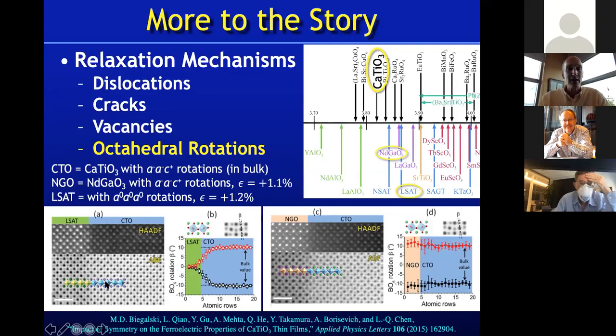Now the reality of the situation is shown by these cross-sectional TEM images, where the authors have mapped out the octahedral rotations, and that's shown in the cartoon on top of the annular bright field data. Here you see a high angle annular dark field, so you can see Z contrast, see the lanthanums in the LSAT substrate. And here the calcium titanate, the calcium is much lower Z, so you also see it, but you can see there's a nice sharp interface. And then looking at the annular bright field to get a better idea of what's going on, in particular with the oxygens, to see those rotations.